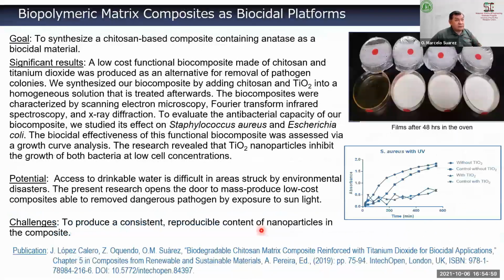I'm going to skip through this, it's too much, and because we were able to synthesize very efficiently these chitosan films, another student started working with the use of chitosan as a substrate for photocatalytic nanoparticles, anatase, that's one of the polymorphs of titanium dioxide, to control the growth of 2 types of bacteria, Staphylococcus and E. coli, gram-positive, gram-negative, and demonstrate that the composite can be efficiently used to control bacterial growth. The student involved got his master's, and now he's working for Procter & Gamble in Ohio. We produced a chapter of a book with those results.